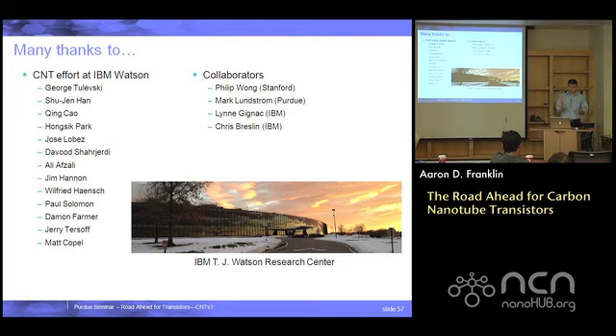And we actually have a paper that'll come out in the next couple months that shows the low voltage potential. Now, low voltage is relative for TFTs. Most of them run at 3 volts or above on backplanes for displays. We show that, hey, you can make TFTs from nanotubes and have the same type of mobility as amorphous silicon, but run it at 1 volt. Which kind of creates a new uniqueness of what you can do there. But yeah, the requirements are much more lenient, and it's interesting in enabling a new space.